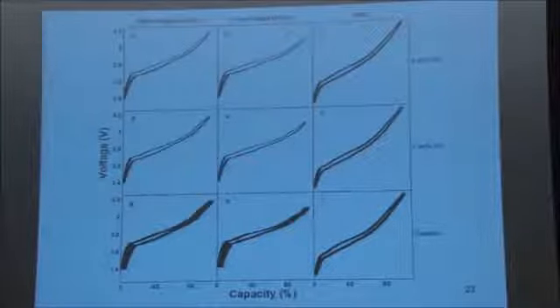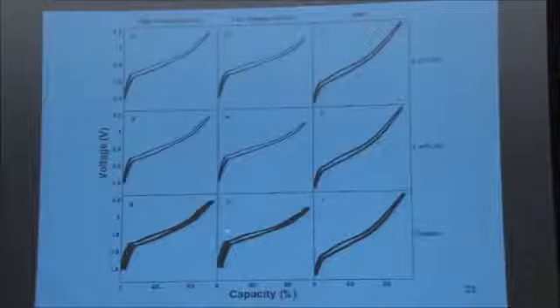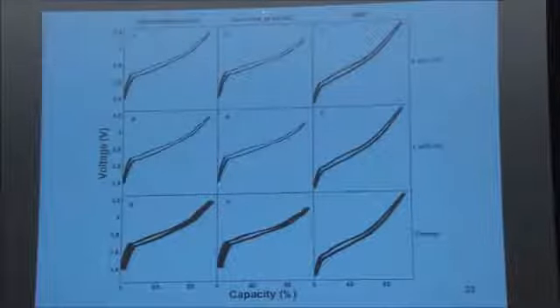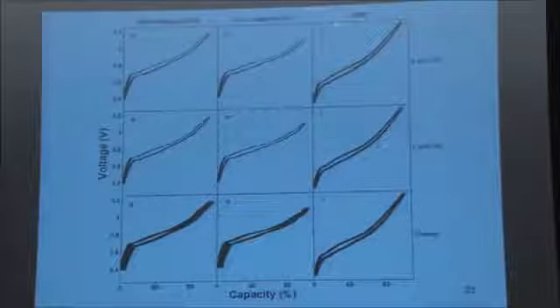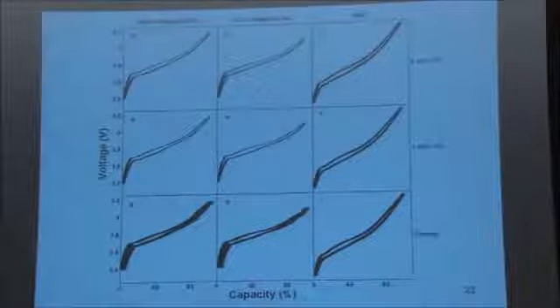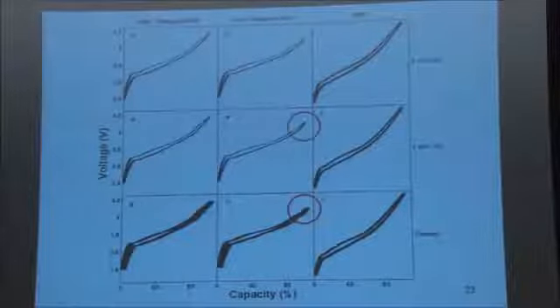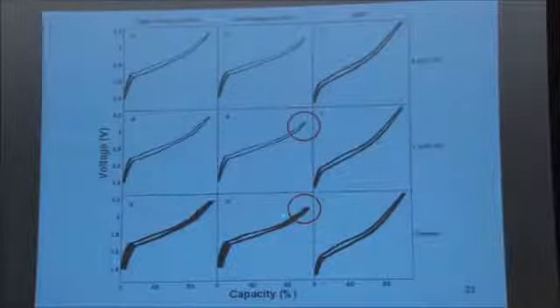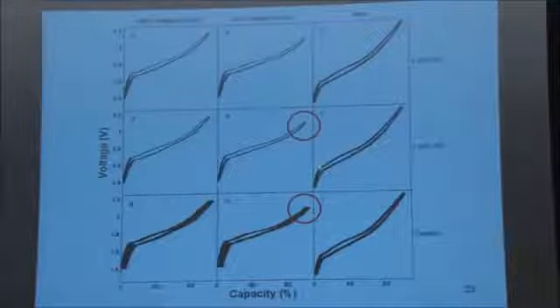Here's some other data. This is for lithium cobalt oxide cells with no vinylene carbonate in the electrolyte, 1% and 2%, and then lithium cobalt oxide cells charged to a lower voltage, and cells that have a nickel manganese cobalt positive electrode. And what I just want to show you here is that when you look at the data, you can see that even 1% of vinylene carbonate really stops that slippage of the voltage curve to the right.